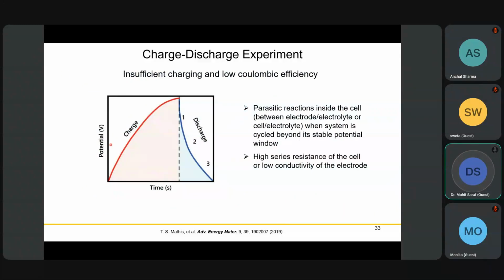This happens either because you are overcharging your cell, or there is insufficient charging, which affects Coulombic efficiency. When you see this, some parasitic reaction starts happening, or some gas evolution occurs, particularly hydrogen and oxygen evolution. It also tells you there is a strong internal series resistance, or maybe it's due to poor conductivity of the electrode. So there might be several reasons.